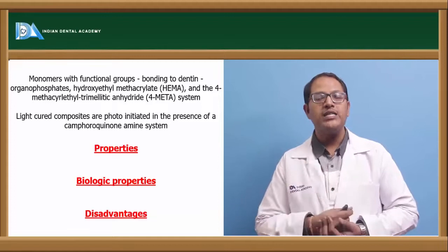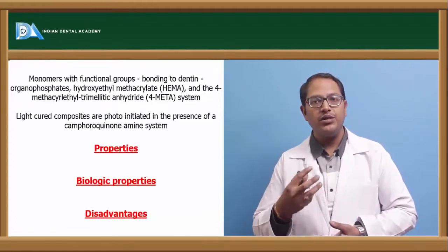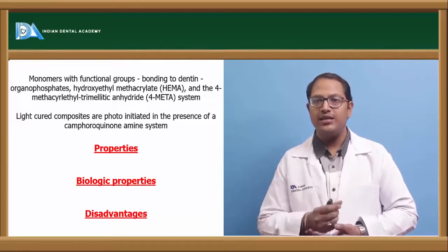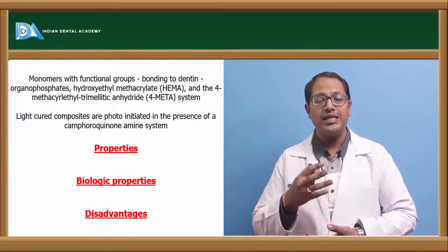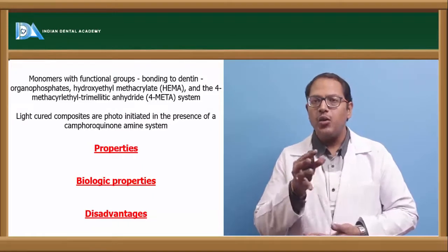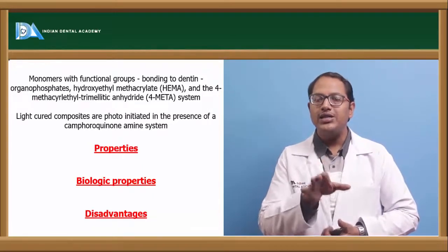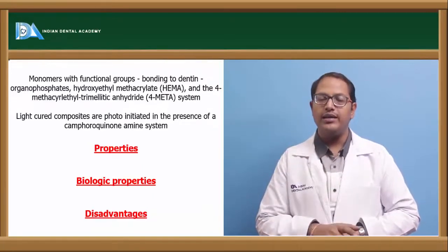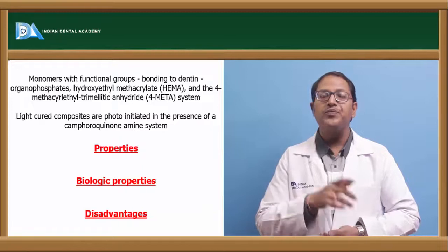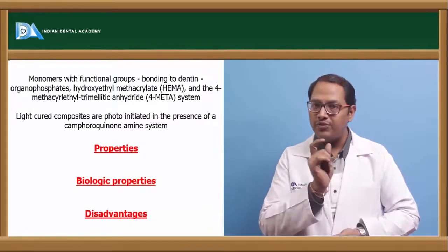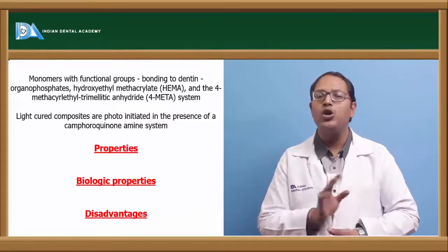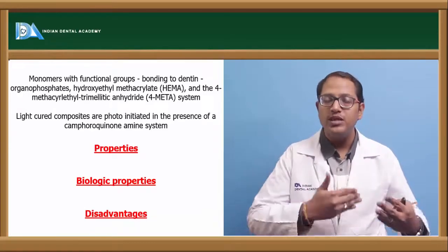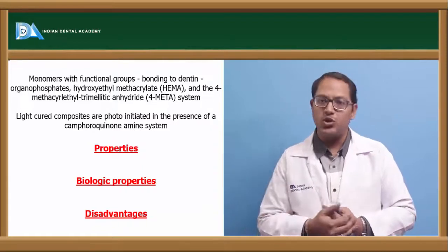Coming to the film thickness part, why is it sensitive and indicated like that? Because we told it's of types, class 1, class 2, class 3. It is self-curing, it is light curing, it is dual curing. Till what level can light curing work? Light curing can work till the thickness is 1.5 mm. Nothing more than that. What will dual cure do? Dual cure can work when the thickness left behind is 2.5 mm. Should not go more than that. So every crown has to be decided based on which material is used. The luting cement choice will differ.